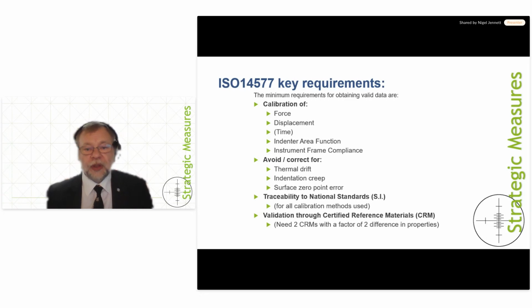And for the full validation of the instrument, you need to have 2 of those with sufficiently separate properties so that you can obtain a low uncertainty frame compliance and a low uncertainty area function without having a sort of circular argument, because you need both to do both.